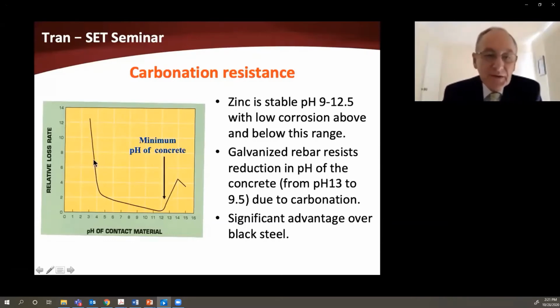And this diagram here, classic diagram, shows the corrosion rate of zinc over different pH ranges. And you can see that zinc has a very low corrosion rate over this range from about pH 9 up to about pH 12.5. So what we find is that zinc is much more able to resist the effects of carbonation, which reduces the pH of concrete from 12.5 to 13, down to about 11. And at 11, black steel in concrete will start to depassivate and corrode. That doesn't happen with zinc because it has this actually increasing corrosion resistance as the pH is reduced.